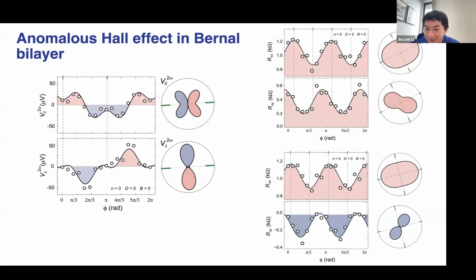A little bit perpendicular, you get canting, but in suspended samples, the state was sort of seen, right? Right. So that's the limit you're working at, right? Yes, but I should point out that the anomalous Hall effect we observe pretty much goes away and transitions to something else at about 50 to 100 millitesla. Right, it's an extremely low field transition.